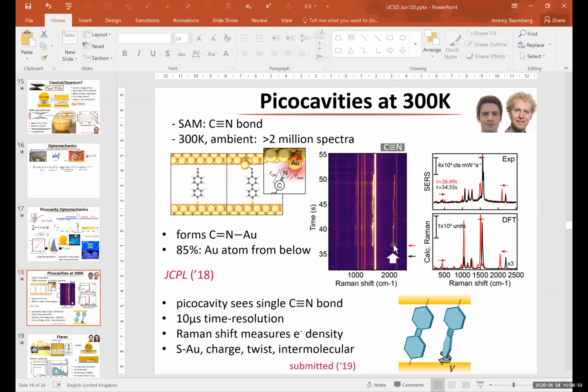One more question. So for this page, you mentioned that you have a single atom on the top layer. How did you determine that? And why does a single atom matter? It's a really interesting question. So what it turns out is that when we make these structures, it doesn't matter what the nanoparticle or the substrate looks like. The forces on here seem to be sufficiently strong that we always get a 1-1-1 surface, we think, on the top and the bottom.